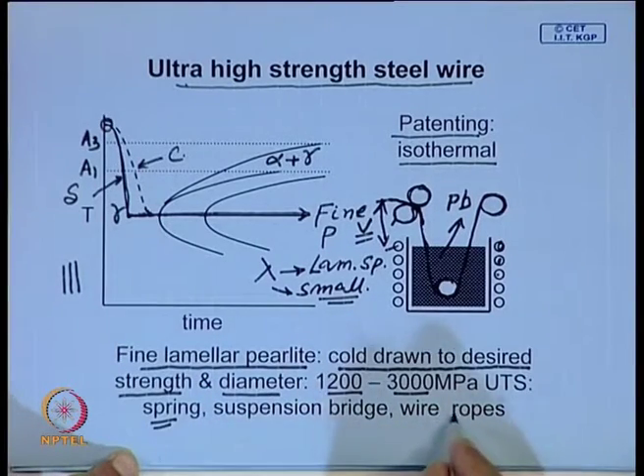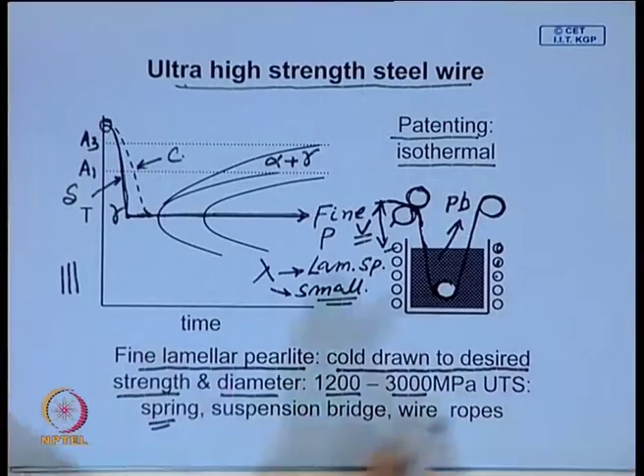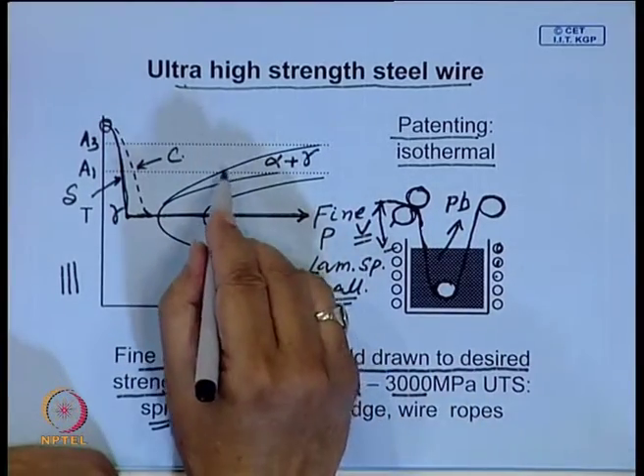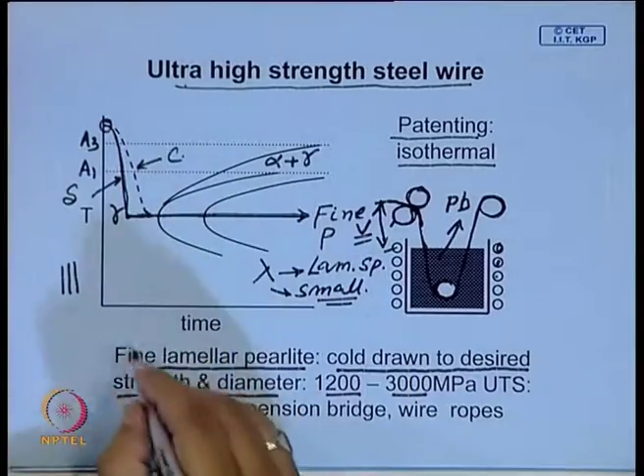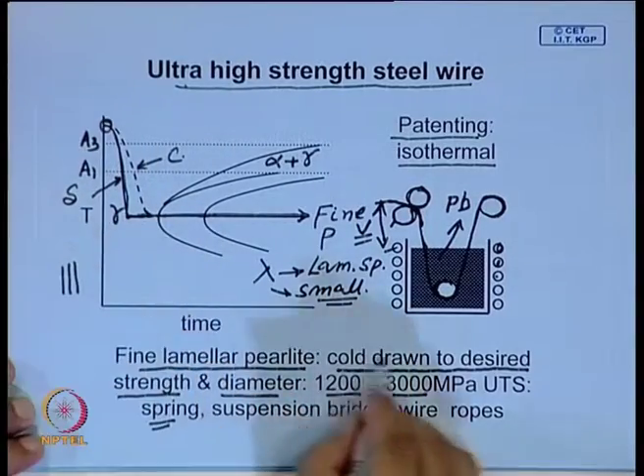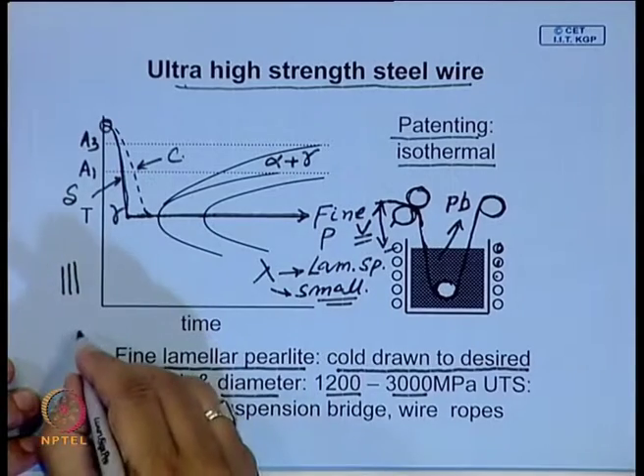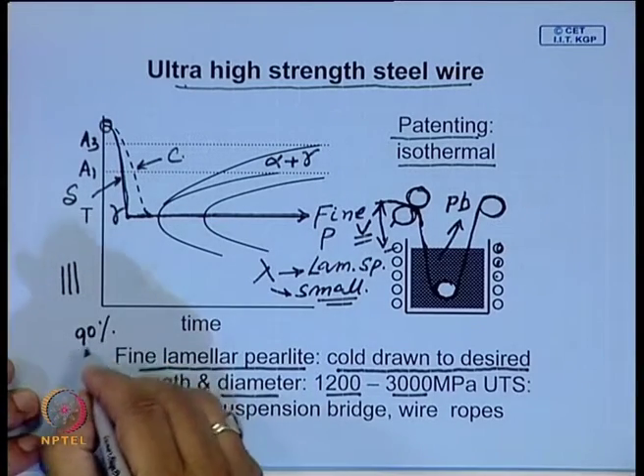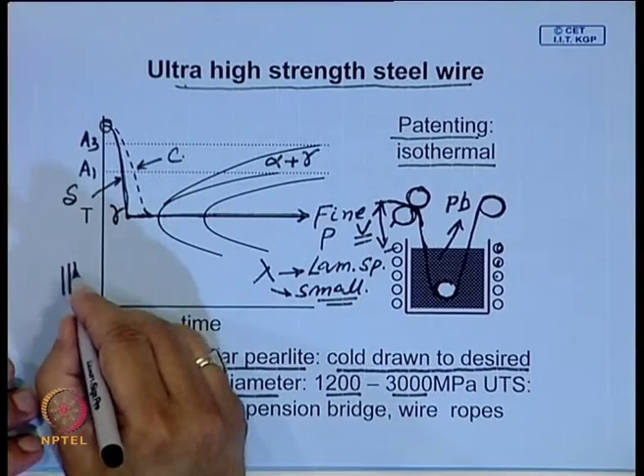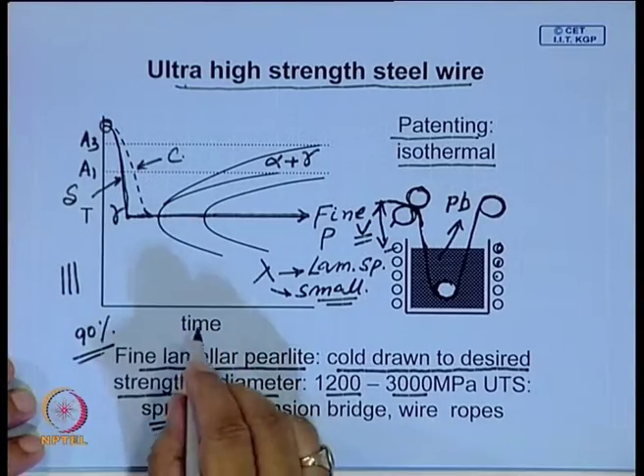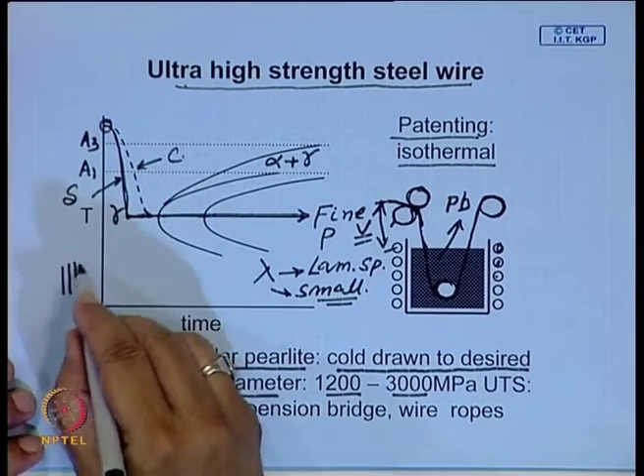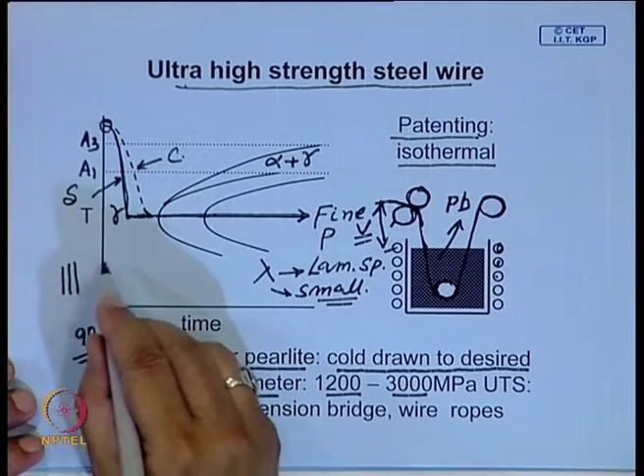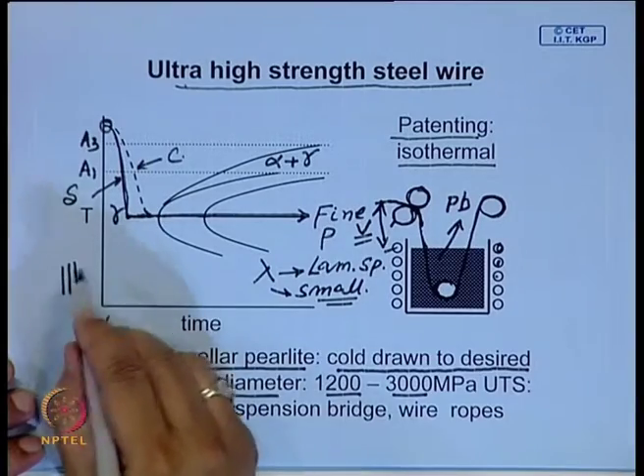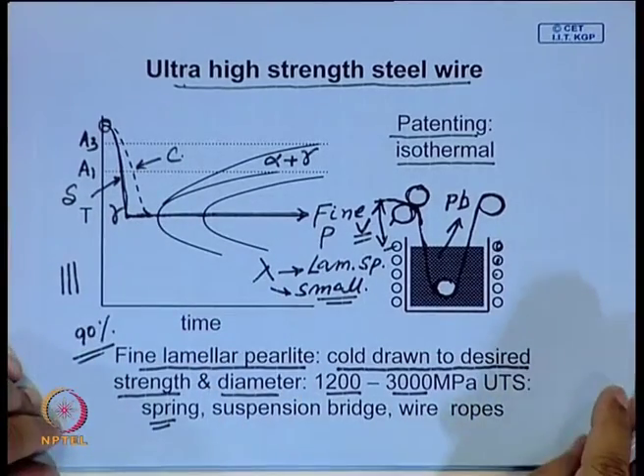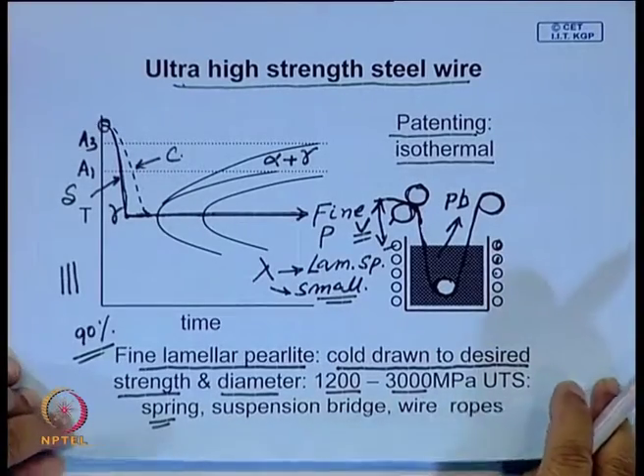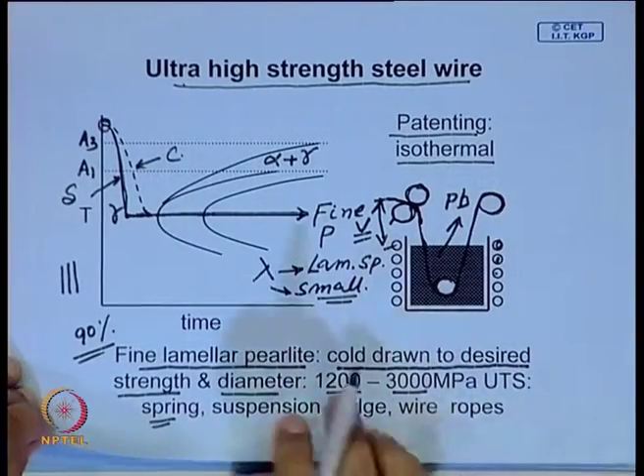then suspension bridges, high tensile wire ropes, and strength will increase definitely as the percentage carbon goes up. In fact, this lamellar, when you give such high cold working, say maybe 90% cold work, these lamellar spacings become even smaller, and in fact, with the transmission electron microscope people have seen, they come out to be of nanoscale dimensions, these spacings, as a result of such large deformations, and that is responsible for such a high level of strength.